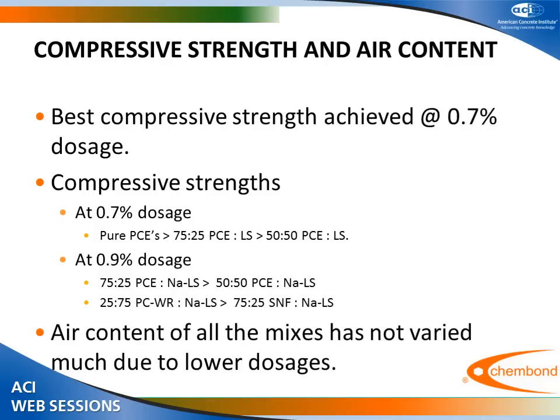At 0.9% dosage, 75-25 PCE, as we have not checked the WR and SR combination, so 75-25 PCE followed by the 50-50 combinations have given good strength results. And most importantly, 75-25 PCWR and NALS combinations have given better strengths than the 75-25 combination of sodium lignosulfonate and SNF. Air content was also under control.